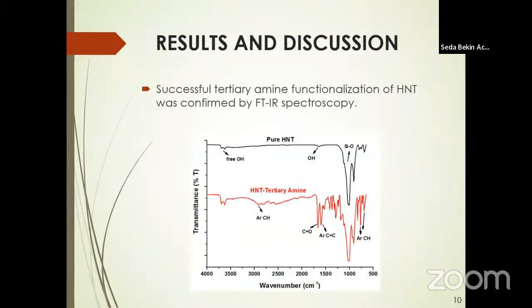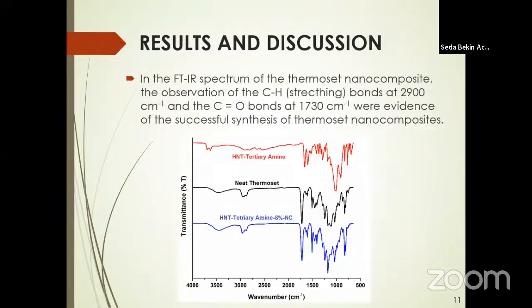After the halloysite tertiary amine was synthesized, the success of the functionalization was confirmed by Fourier-transform infrared spectroscopy. According to this, aromatic CH, carbonyl, and aromatic CC peaks were observed in the spectrum of the functional nanofiller. In addition, Fourier-transform infrared spectroscopy was also performed for the thermoset nanocomposite. In the FTIR spectrum of the thermoset polymer, the observation of the CH and CO bonds was evidence of the successful synthesis of thermoset nanocomposites.